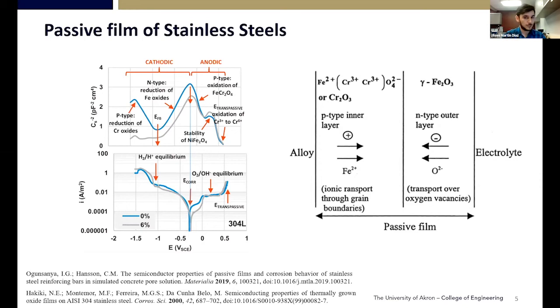However, as we get close to the Ecorr, we are reaching the N-type semiconductor, which are the iron oxide, which are semiconductors that tend to donate, making the passive film more doped and less protective. If we reach the anodic potential, we start actually dissolving the spinel phase to then continue with this chromium layer, depleting even more the corrosion properties of our metal.